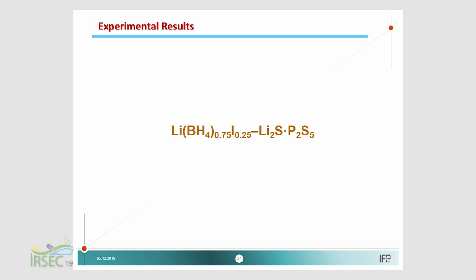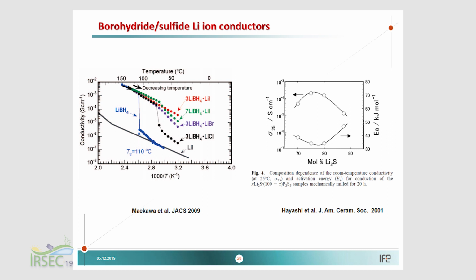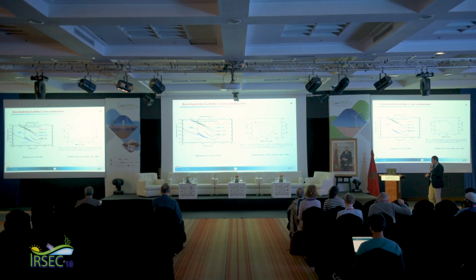We start with some materials based on lithium borohydride iodide and lithium sulfide phosphorus sulfide. The idea comes from the fact that this lithium sulfide electrolyte, which is known in the literature, has some stability issues, so we tried to mix it with the lithium borohydride system. We wanted a system with monotonically increasing conductivity, which is rather normal in battery systems. No one wants a phase transition when using the battery at different temperatures.